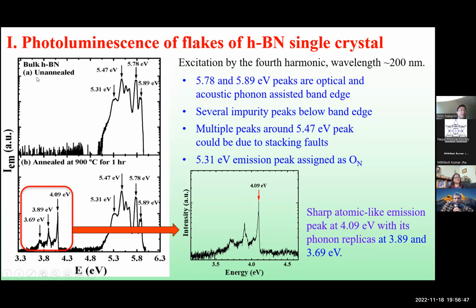The first sample is an unannealed sample. This is exactly the sample we got from our collaborator. After that, we annealed it. Anneal means we heat up the sample at 900 degrees C for 1 hour. The idea was to improve the crystalline quality. Then what we got is a special kind of emission, with a sharp peak at 4.09 eV.